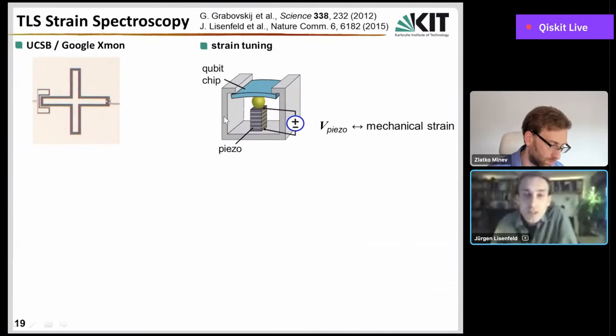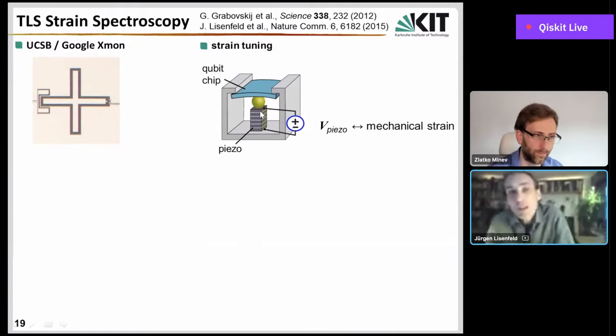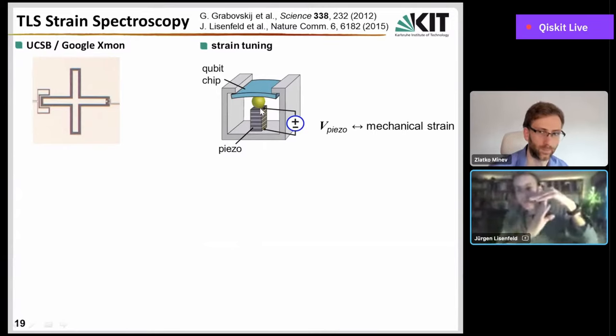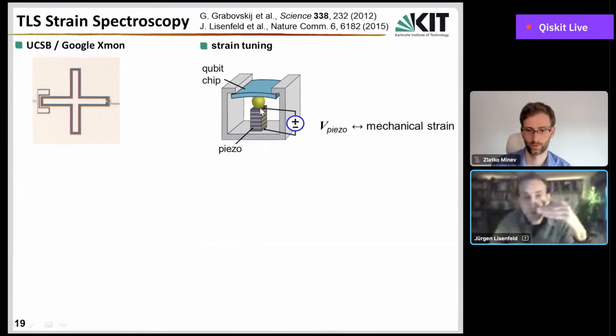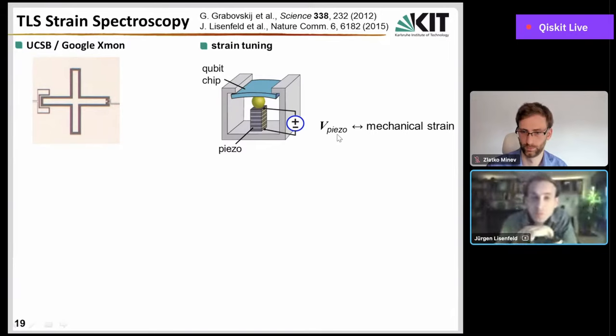We tried this simply by installing our qubit chip in such a metallic holder. On the backside, we had a piezo actuator, which was just pressing against this qubit chip. If you apply a voltage, the piezo gets longer, and therefore we could tune the force by which the piezo is pressing against this chip just by a voltage source. So this means we can control the mechanical strain by this applied piezo voltage.